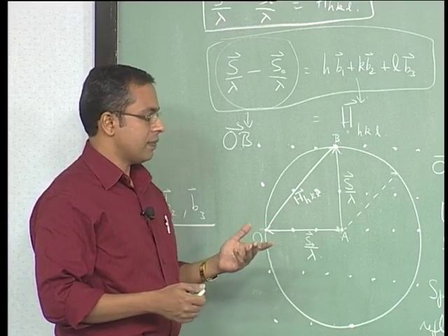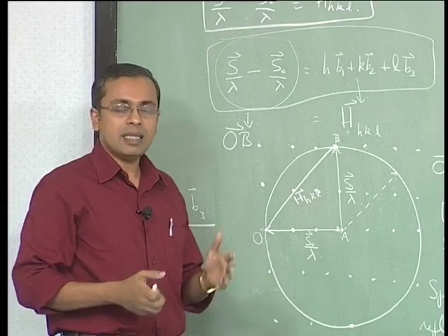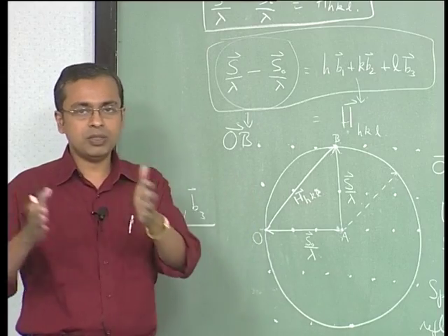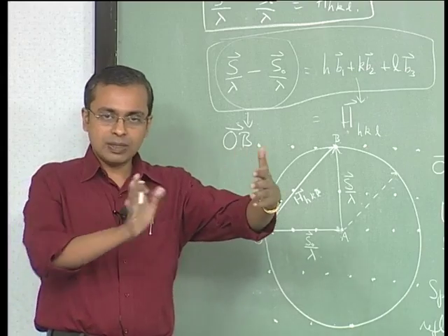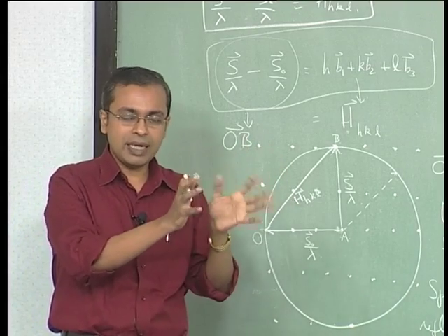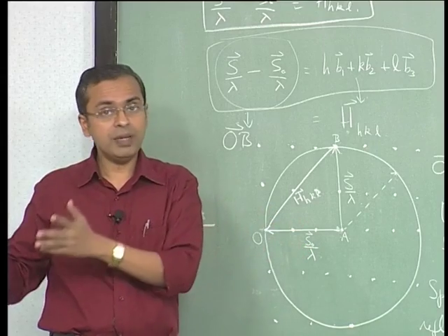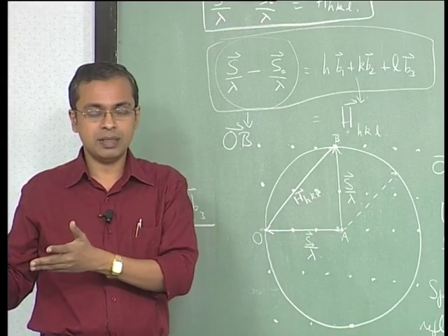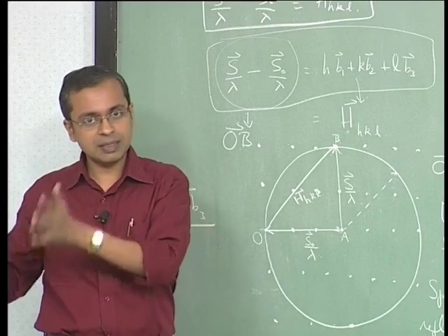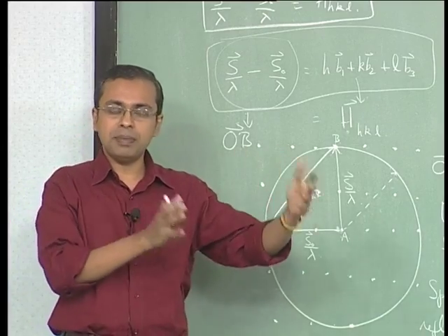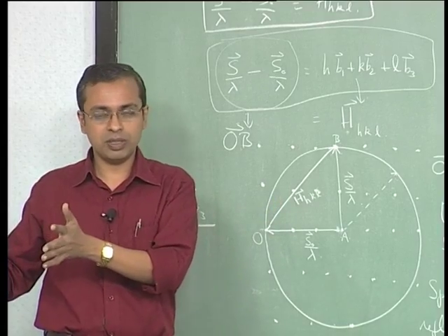We have also seen in this class that when you do this transformation from real space to reciprocal space, a structure that has a certain geometrical layout in real space may have a different geometrical layout in reciprocal space. In the case of simple cubic, it happens to have the same layout. In the case of FCC and BCC, it has a different layout in reciprocal space.